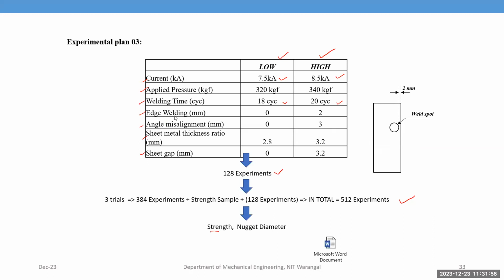And here you can also go with 2 mm edge welding. Then angle misalignment 0 and misalignment 3. Intentionally, we are giving the 3 sheet metal thickness ratio 2.8, 3.2, and the sheet gap, you can see, 0 and 3.2. So you can go with this as a two-level experiment. There are 7 parameters, so the minimum number of experiments required to run the process is 2 to the power of 7, which is 128 experiments.